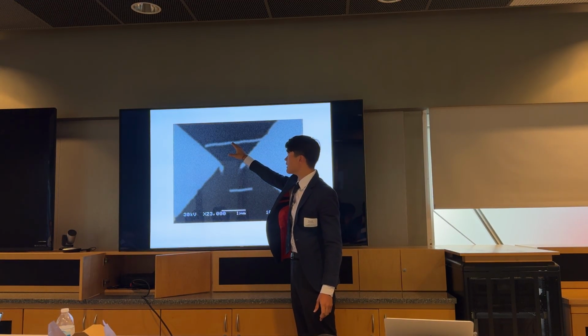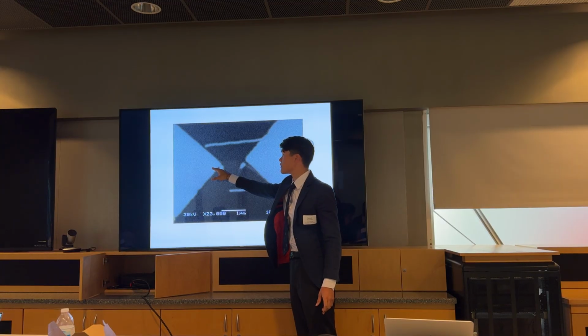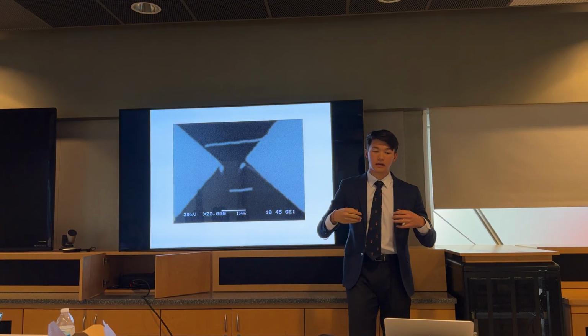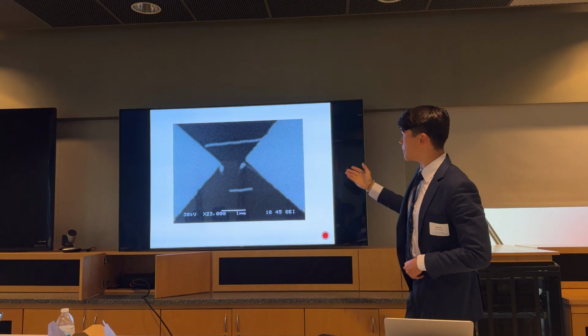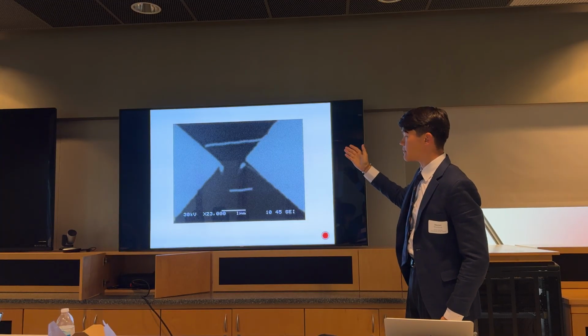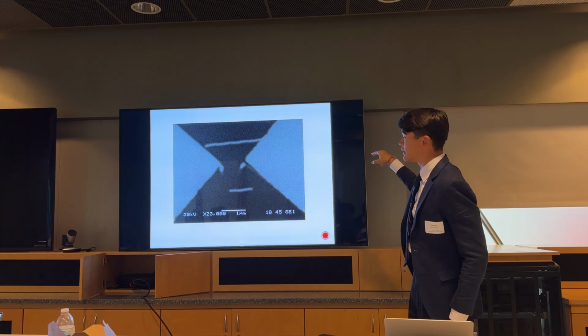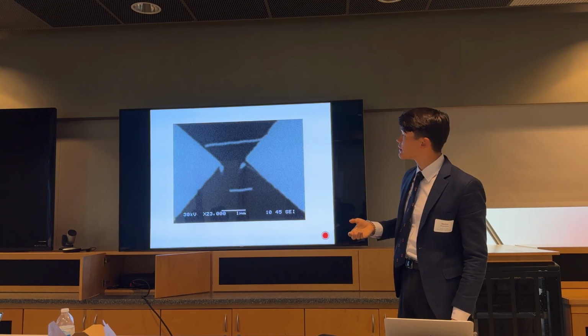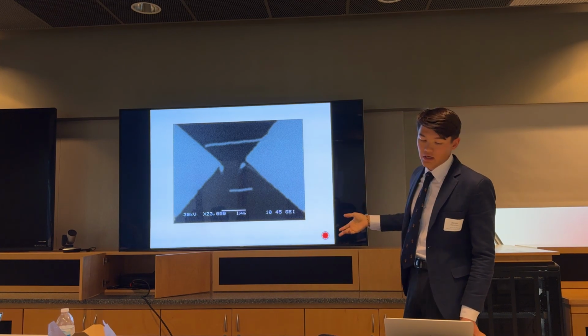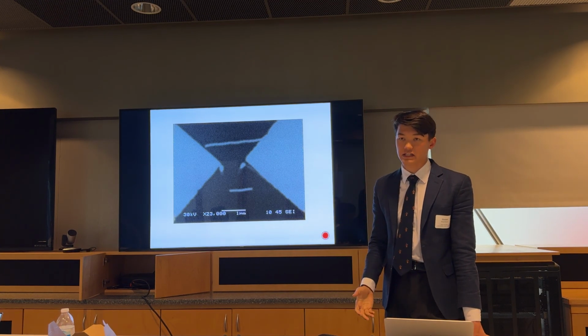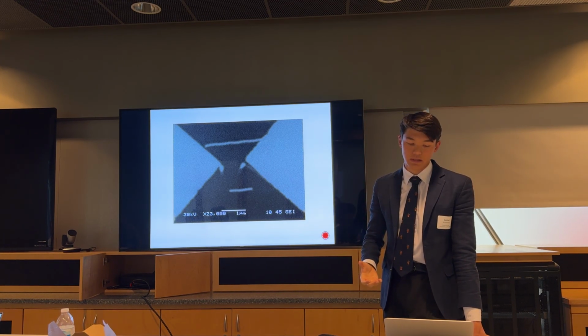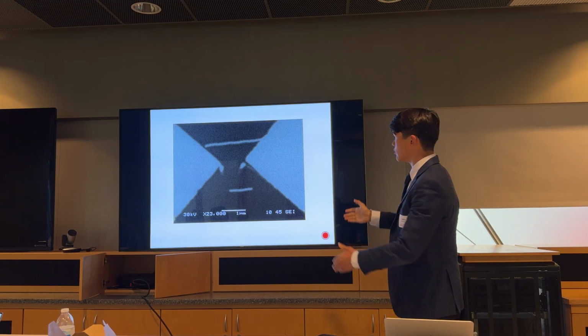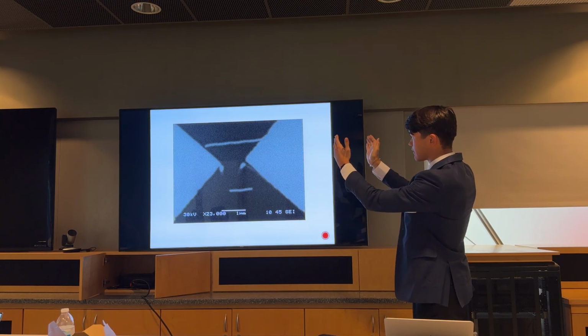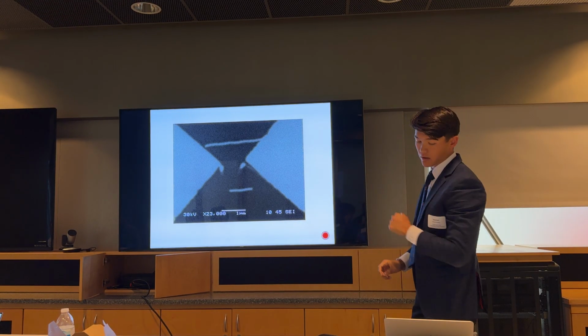So it's necessary that this makes contact with the rest of the pads so that electrical connections can be made. And the reason for this misalignment was because I wrote the line in the middle at a different beam current as the main contact pads. So in the future, when I make a contact pattern like this again, I should either choose a unified beam current or create flatter sides of the contact pads so that there is some leeway with misalignment.